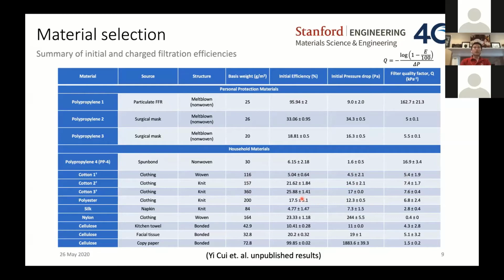Particularly, let's look at cotton 3 right here. 26% of filtration efficiency, 17 Pa of pressure drop. And imagine you take this cotton 2 layers together, and you can actually reach about 40% of filtration efficiency. Pressure drop doubles, about 34 Pa. And you can have a facial mask for particle filtration reaching close to surgical mask already.